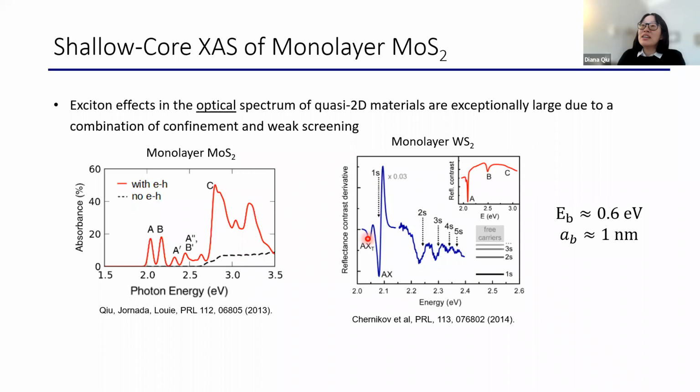That's a good point. Essentially, what we do is we look at the exciton wave function, and we characterize them as 1s, as this Rydberg series, based on the nodal structure of the exciton wave function. I don't have that in a slide here, but it's very, very obvious from the wave function. Another way you can characterize the angular momentum of the exciton wave function is by looking at transitions. Here I was saying A prime and A double prime are the 1s, 2s, 3s states, because the s states are the ones that are bright under single photon absorption.